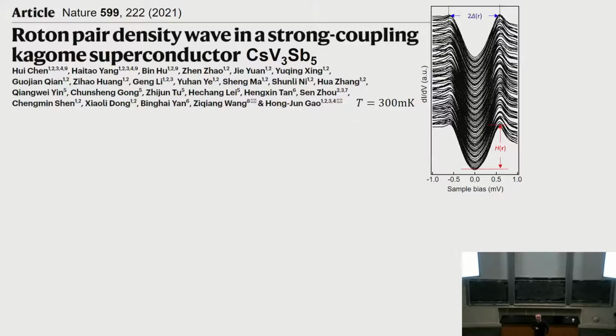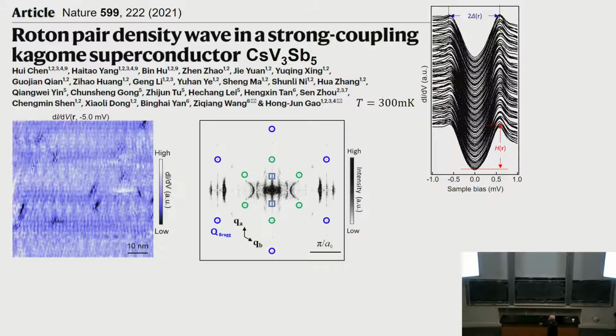So let's look at the superconducting state. This is the spectrum of the density of states in the superconductor. It's not really a BCS-like superconductor with a full gap. It looks like it has some sort of a V shape, but with finite density of states at the bottom. So this is a conductance at 5 millivolts, dI/dV map. You do the Fourier transform of that. You see the Bragg peaks. Right? You see the CDW peaks. So CDW coexists with superconductivity.